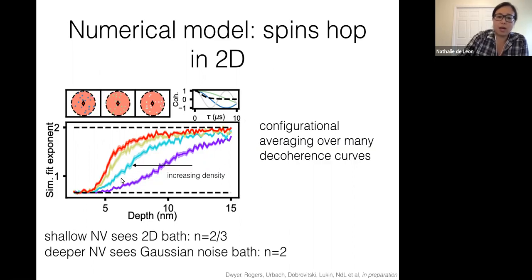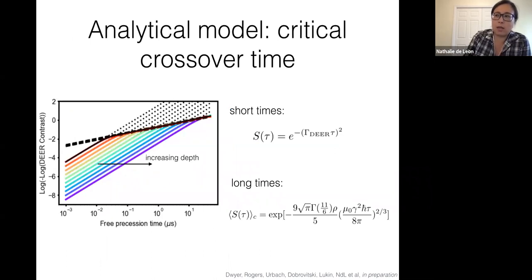And then the depth at which you see this transition point should depend roughly on the density of spins at the surface, because that sets the relevant length scale. And indeed, as you increase the density, you can see that this depth gets shallower and shallower. Okay, so those are the numerics. We can also put together an analytical model for this dipolar coupled bath. You get an integral that's not very easy to solve directly, but what we can do is solve it for very short times and for very long times. In these two limits, at short times, we get, again, this nominal model of n equals 2. And for very long times, we do indeed get this n of 2/3.